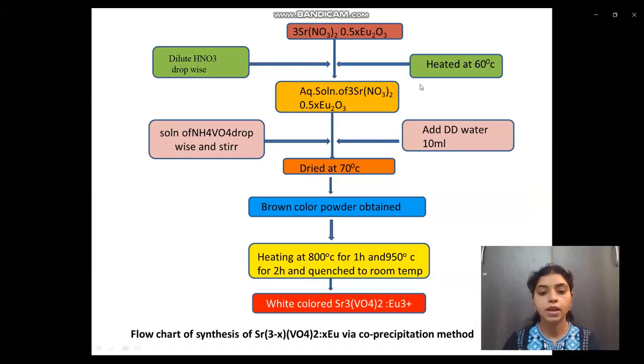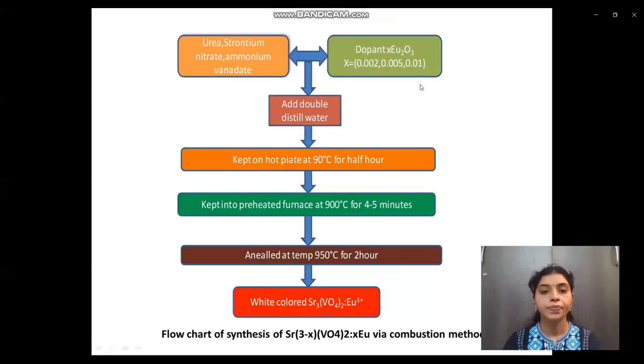Then this is a flowchart for the combustion method. In this method, the precursors, urea, strontium nitrate, ammonium vanadate, and also the rare earth material, are mixed together in a crucible, and some double distilled water is added to this mixture. Then it is kept on a hot plate at 90 degrees centigrade for half an hour, and this mixture was then kept in a preheated furnace at 900 degrees centigrade for 4 to 5 minutes so that a complete redox reaction was obtained, and then annealed at 950 degrees centigrade for 2 hours. Finally, the white colored product is obtained.